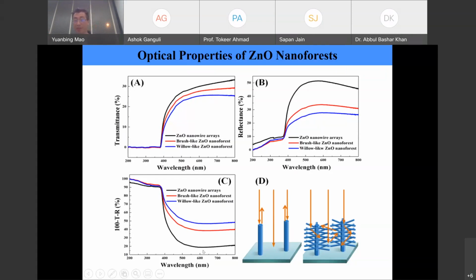So how do we explain that? If I show you schematically, then that will be much easier. This type of nanowire array, because they are not dense enough, the transmittance is highest. And also because of the ends of these nanowires, they could have quite a higher reflectance.